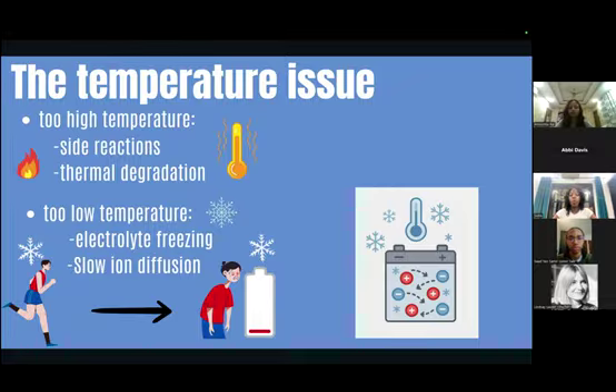When the battery becomes too cold, even before the electrolytes freeze, the cold makes it more viscous, a bit like a honey-like texture. And this sluggish movement means that our battery can't deliver power effectively. And most dangerously, if we try charging a really cold battery, instead of the ions moving smoothly and embedding in the anodes, they plate as metal, and this will form dendrites that can pierce the separator and cause short circuits. So we decided that we are going to focus more on how to fix the low temperature issue for sodium-ion batteries.